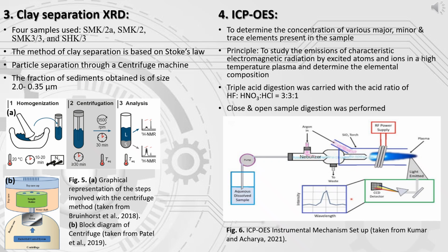Therefore, clay separation using a centrifuge machine was done to separate the smaller particles from coarser ones. The method is based on Stokes' law. The supernatant on centrifugation contained the smaller particles, which are 2 to 0.35 micrometers small. The prepared sample was sent for X-ray diffraction.